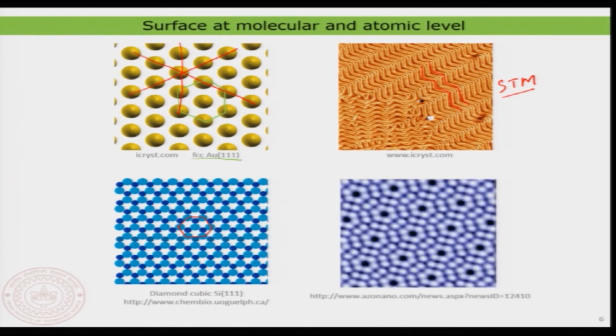Or if you look at the silicon 111 surface, as expected you would have seen basically a hexagon, but instead what you are seeing is a much larger hexagon, but the arrangement of the atoms looks entirely different than in the expectation. It is also due to the fact that the atoms on the surface undergo a rearrangement due to something called reconstruction, and the surface then gives rise to an entirely different microscopic structure than what is expected. So again at the microscopic level you see that there is a huge difference in the way the atoms are arranged on the surface.